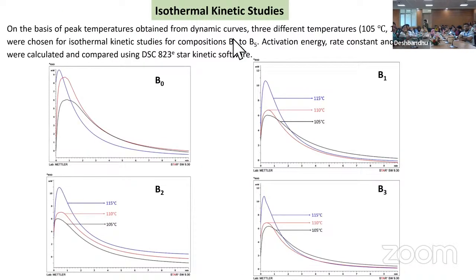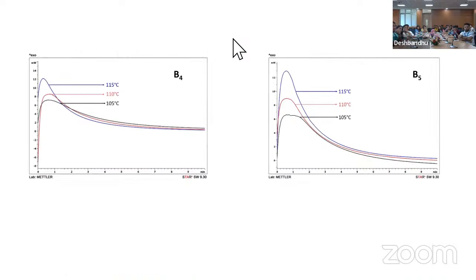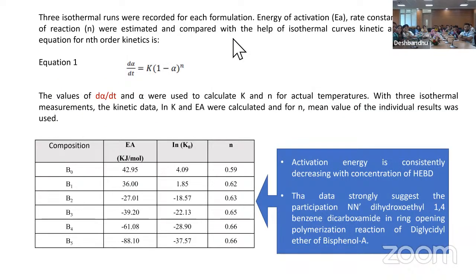So on the basis of dynamic curve thermograms, we have selected 3 temperatures for isothermal kinetic studies, 105, 110, 115, these 3 temperatures. At these 3 temperatures, 3 thermograms were recorded for each formulation. And these are overlaid here for calculation of activation energy, rate constant, and order of reaction. B4, B5. So this is the data tabulated here.